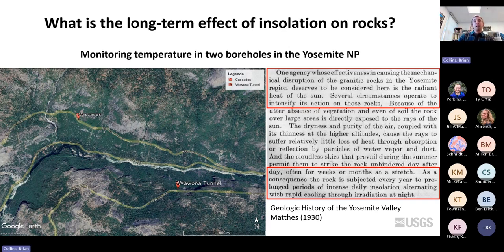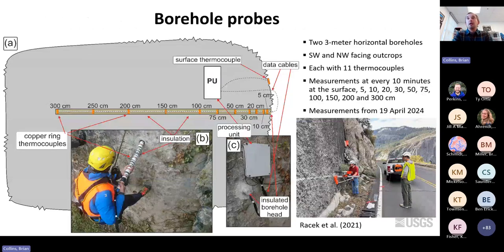To observe this, we installed 2 boreholes. One is southwest facing next to the Big Oak Flat Road, and the other one is northwest facing next to the Wawona Tunnel. And in each borehole there are 11 thermocouples measuring temperature every 10 minutes. One is on the surface, one is at 5, 10, 20, 30, 50, 75, 100, 150, 200, and 300 centimeters at depth. And the measurement started in the second half of April.